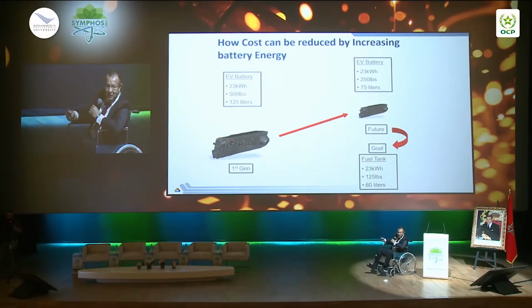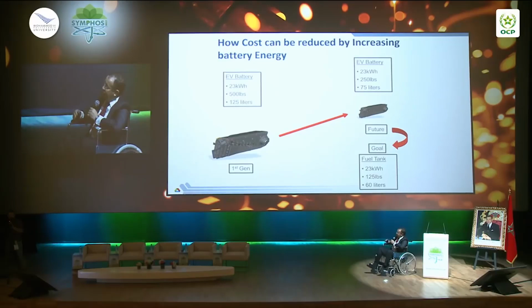A lot of people in the academia, at least, refer to iron phosphate as a cheap material, and therefore the cost is low. This is very misleading because the cost of a cathode in a pack is only 10%. So if you remove completely the cathode, you reduce the cost by 10%. You don't have a battery anyway. But if you do it this way, you reduce the cost across the board. You see, we reduce the weight by almost half. And that's really cost, because these are materials, including inactive like current collectors, copper, aluminum, separator, and so on. So we really need to increase the energy. Now, I have shown you how to increase the energy of the iron phosphate by designing unique morphology. But there is also an opportunity by increasing the energy, either by increasing the capacity of the material or increasing the voltage.